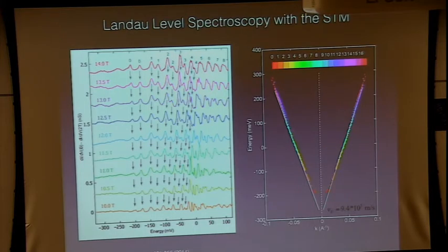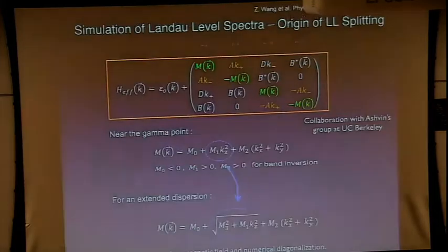And we could do this very nicely for cadmium arsenide. This is a very nice example of using STM to measure, with very high energy resolution, basically the band structure. This is a bulk band structure. I don't know why this is so extremely linear in this compound. It's linear over a very large energy window. I don't think this is really anything but maybe an accident of the band structure. It's supposed to be linear only near the Dirac point, but this is somehow linear over a very large energy window. And that's consistent with what our ARPES colleagues see as well.